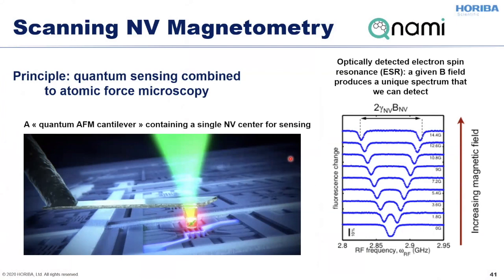And as a result, if we add the RF excitation in the vicinity of the apex of this probe that has a single NV center, then we can probe the distribution of magnetic field in the sample based on the spectral signature, based on the dependence of the photoluminescent spectrum on the RF frequency with which the junction of the tip and the sample is excited. And the ultimate sensitivity of this technique was claimed to be down to actually a single spin of an electron. Therefore, this technique allows us to measure distribution of the magnetic field even in normally very weak magnetic materials like antiferromagnetics, superparamagnetics, and so forth.